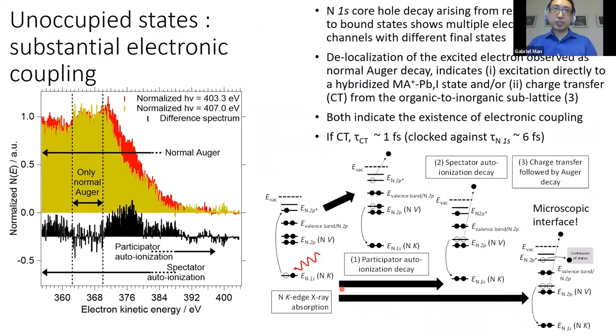A different picture emerges when we look at the unoccupied states. This is a comparison of two Auger and Auger-like spectra. The red one is associated with a resonant excitation at 403, and the 407 should be just normal Auger. If we take a difference spectrum, we get these extra features over here, and we can assign them to spectator autoionization and participator autoionization. But the key thing here is that there's actually a rather large component of normal Auger decay.